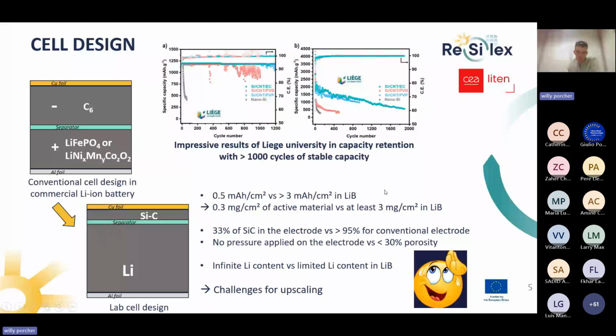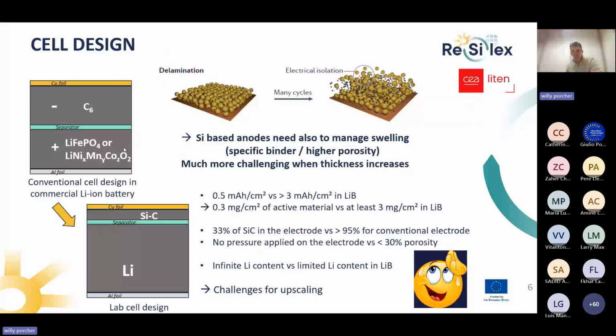Also, in this result presented, there was only a third of active material compared to the 95% that we usually expect. There was no pressure applied on the electrode, compared to the 30% porosity that we usually target. The main point is that it's tested versus lithium metal, so there is an infinite lithium quantity in this setup, compared to a real lithium-ion battery, in which we have a limited lithium quantity. So when we assemble a lithium-ion cell with high energy density, we have a real challenge to address, particularly with silicon, with this swelling: we need to keep all the particles connected with a significant thickness of the layers.